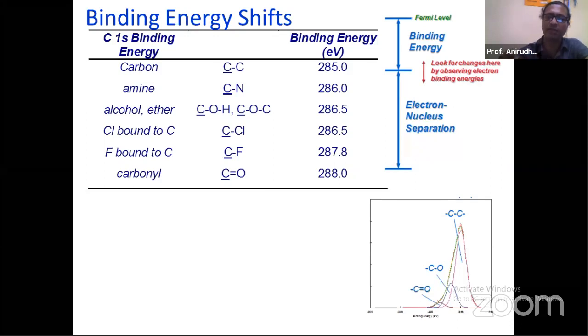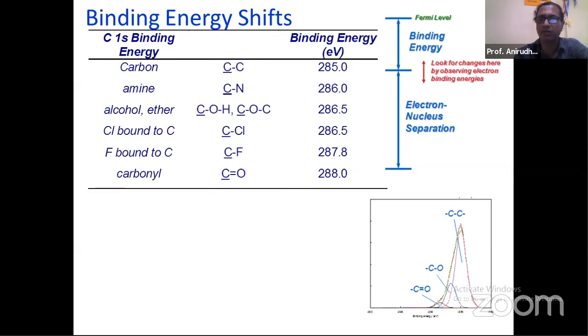And then you have to establish the presence of those elements also. With this information, you can combine all of them to say that, you see, carbon is getting bonded to nitrogen, or carbon has formed a bond with chlorine, because the carbon 1s binding energy from my XPS experiment for this tribological interface is giving a value of, let's say, 286.5, and things like that.